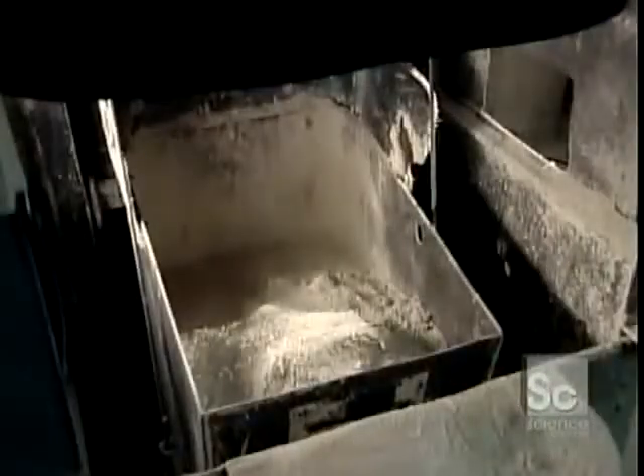The ingredients go into a mixer where they're hydrated until there's 6% water to 94% powder. The mixer runs for precisely 12 minutes. Any longer would heat the mixture and dry it out.